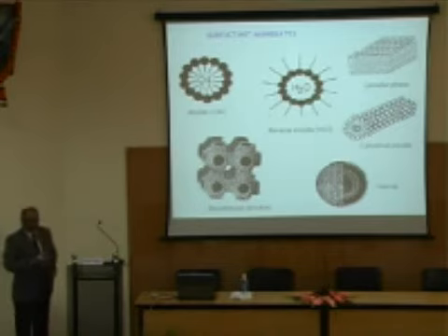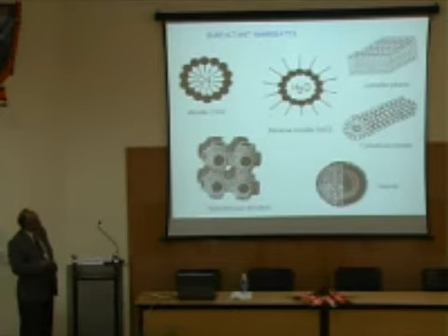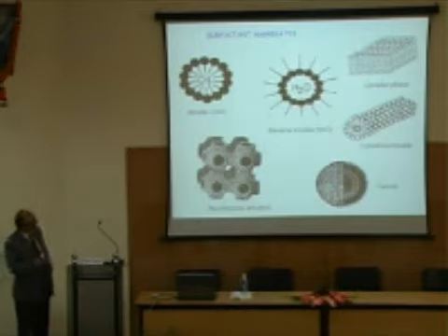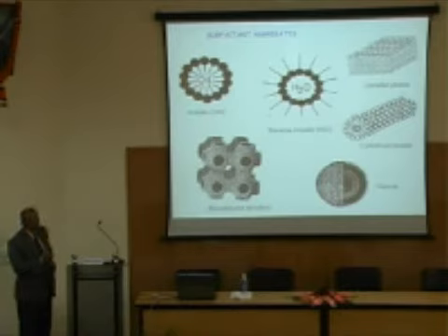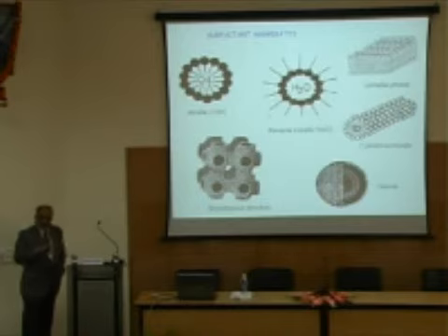So, other than spherical structures, as I said, this is the most popular structure which is used, which is spherical, and it is called a reverse micelle, because this is pointing inside. If it points outside, it is called a micelle. This is just terminology, but you must know that when it points inside, since it likes water, water has to be inside, water cannot be outside. If it points outside, then water has to be outside, and no water can go inside, only oil can go inside. So, that restricts the kind of synthesis that you will do by designing this.